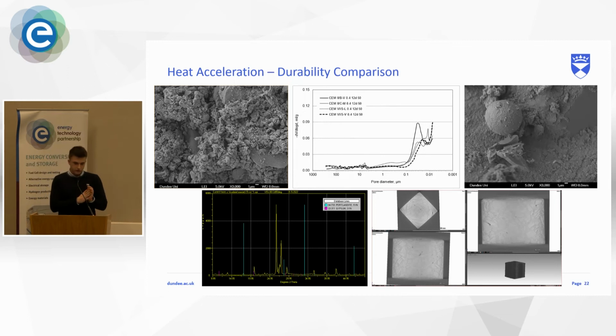So what is left to do now is to compare the microstructure of the 12-day cure at 50 degrees with the 90-day standard cure at 20 degrees samples, and to see whether durability matches. To assess durability, we have to look at the microstructure of the sample. So we have to really look up close at the concrete, measure its porosity, and try to understand what's going on inside of it.